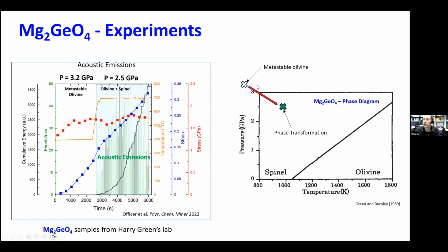But then once we reach about 10% strain, we're building up some elastic strain in the sample. Then we increase the temperature, we initiate the transformation, and all of a sudden you see over 1,000 acoustic emissions. So the sample just starts to break once you initiate the phase transformation.